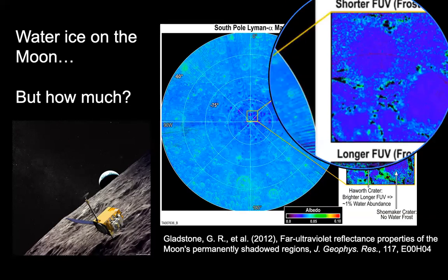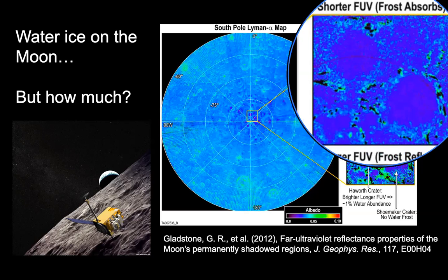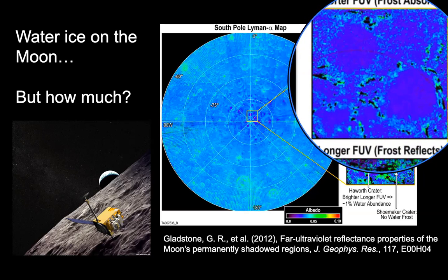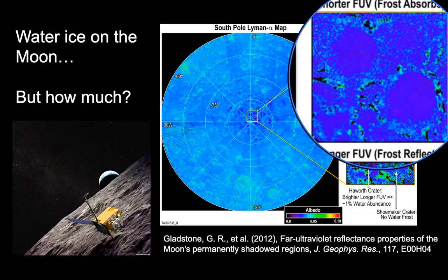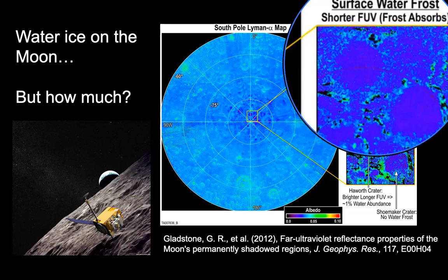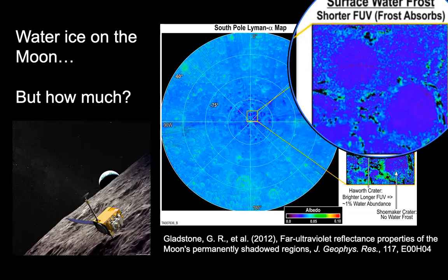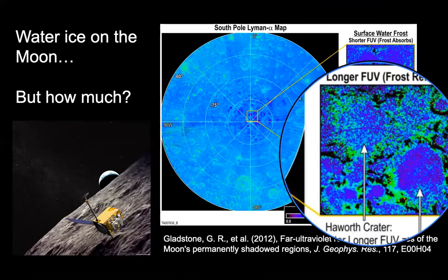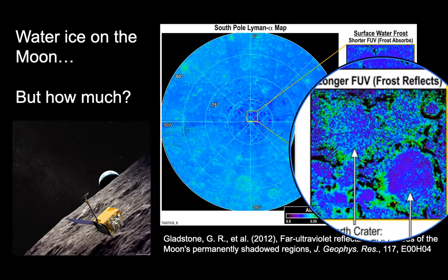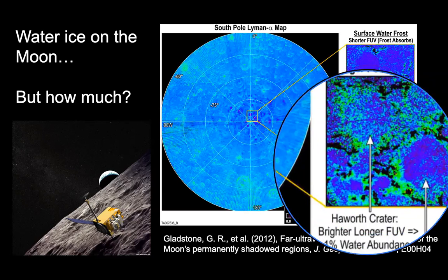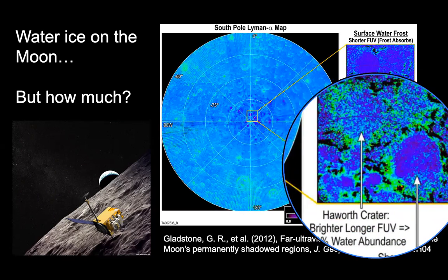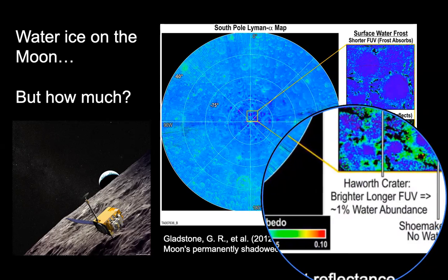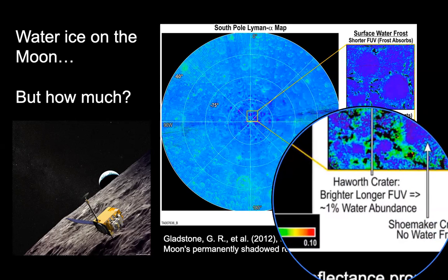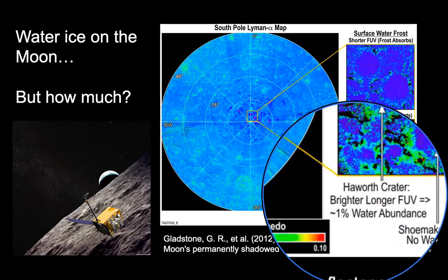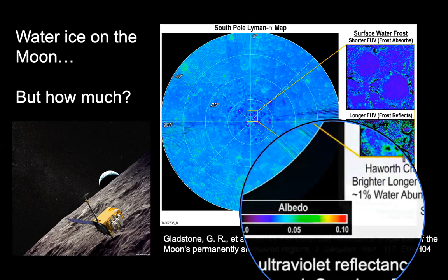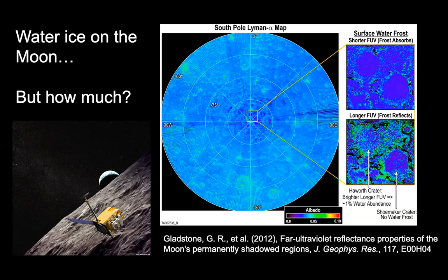So in the shorter UV, you notice in this image that there is not a lot of difference in the coloration there. And that resembles very low albedo, very low reflectance, all right? So in shorter, far ultraviolet, frost absorbs. But in the longer FUV, you start seeing something very different. You actually see that there are regions where that reflectance increases quite a bit. And that implies a roughly 1% water abundance. Now, I want to highlight that as roughly 1%, okay? And that's a key fact here, that it is roughly.